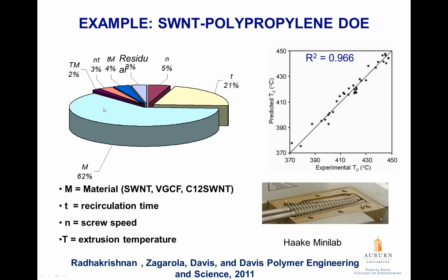So here what we found was that if we looked at the thermal decomposition temperature, or the temperature at which the material would start decomposing, the material had the biggest role in the process, but also the recirculation time, which affected both mixing and polymer degradation. And there were also some interaction terms. That was both temperature and the material had an interaction. And we can develop models using design of experiments, predictive models, where we can get an equation that will give us a predicted thermal decomposition temperature versus experimental values so that we don't need to test every single point.